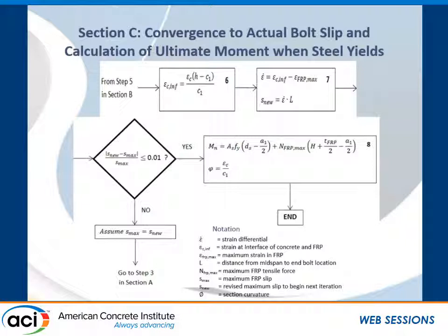This is the concrete strain. It's calculated based on linearity of strains. And then the strain differential, the epsilon dot in the next box here. Our strain differential is the difference between the calculated strain at the concrete-FRP interface and the maximum strain in the FRP that was calculated from the maximum FRP tensile force. The strain differential is then used to calculate a revised slip in the connection.